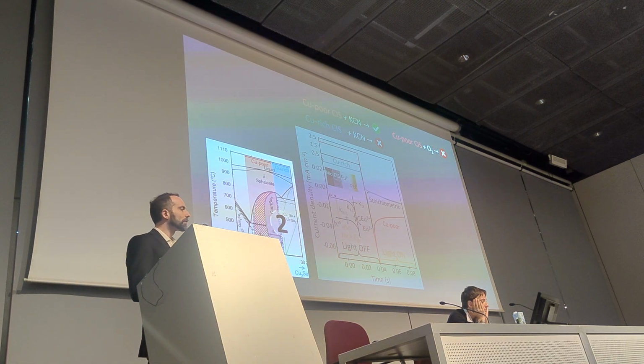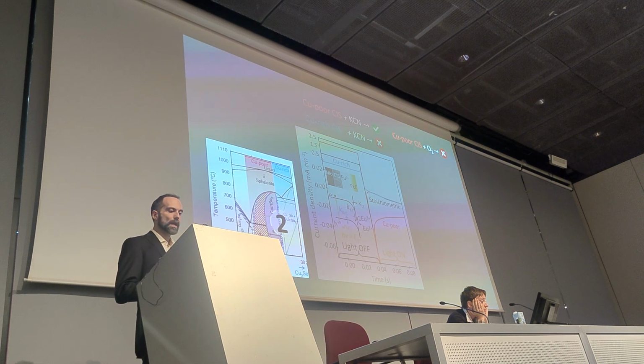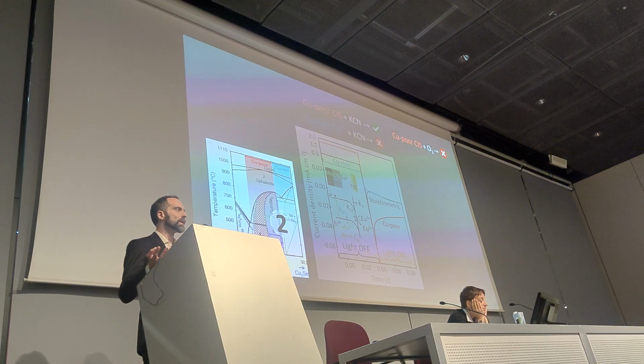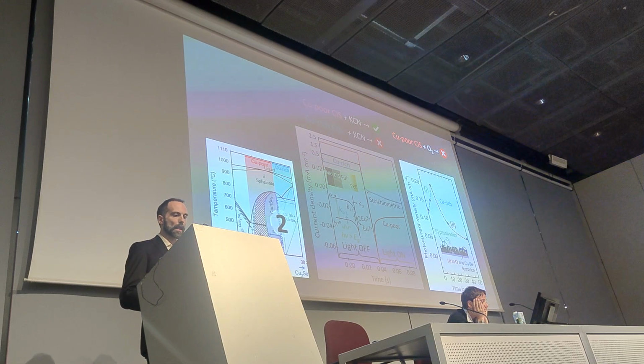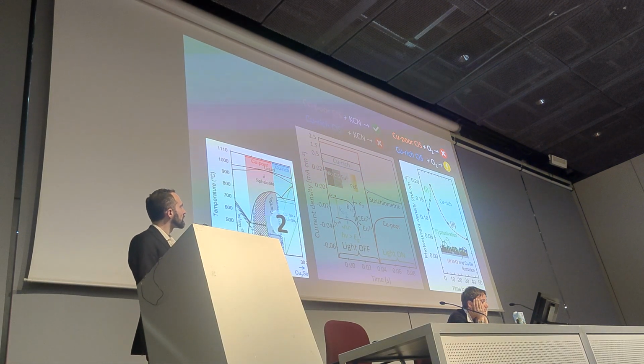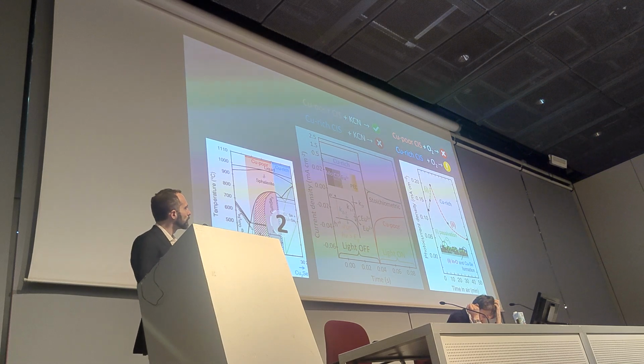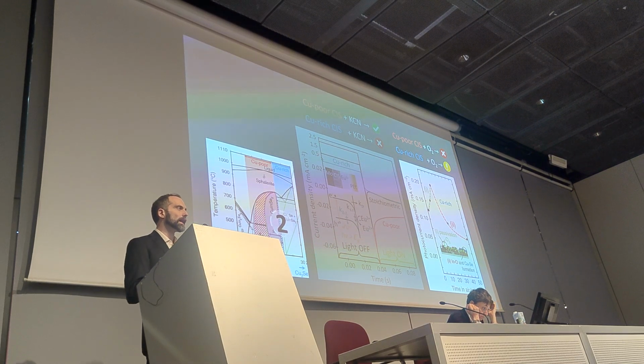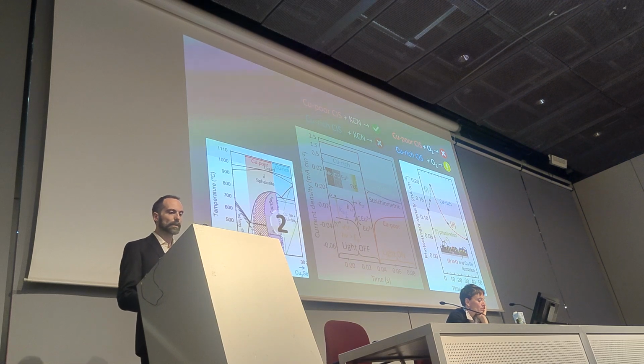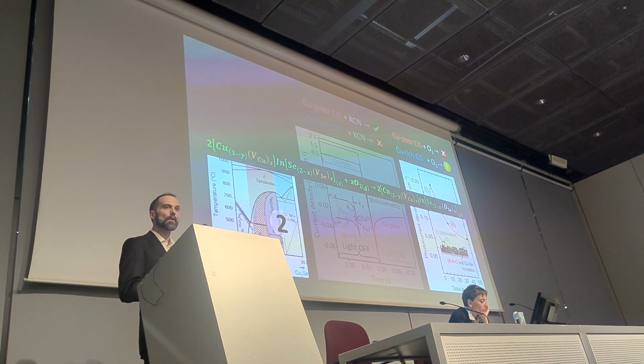We decided to perform a simple experiment, just exposing these films to air and seeing what happens. If we expose a copper poor film to air, this generally always leads to a poorer performance. But what happens now if we expose the copper-rich film that was previously etched with potassium cyanide to air? What we observe initially is an improvement of the performance, and then a drop. So clearly oxygen is doing something, and this defect that we have generated has an affinity to oxygen.